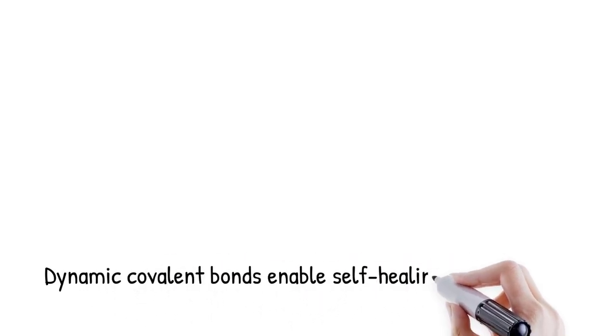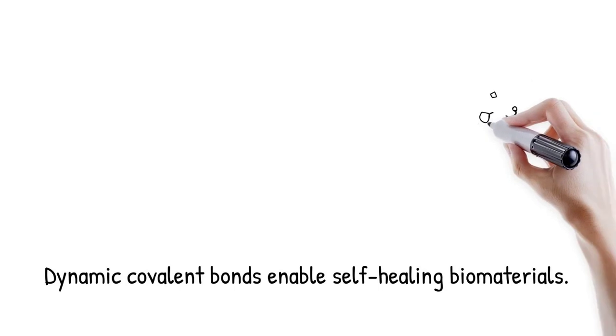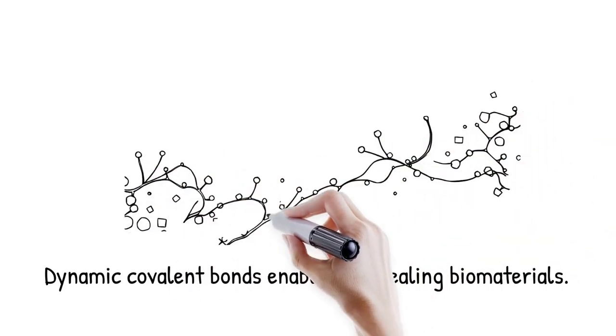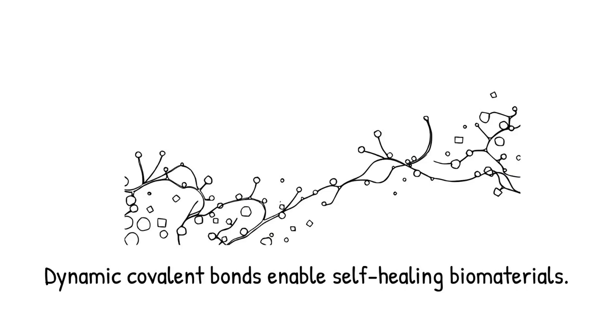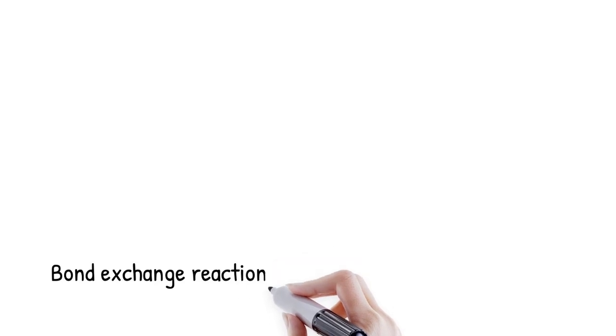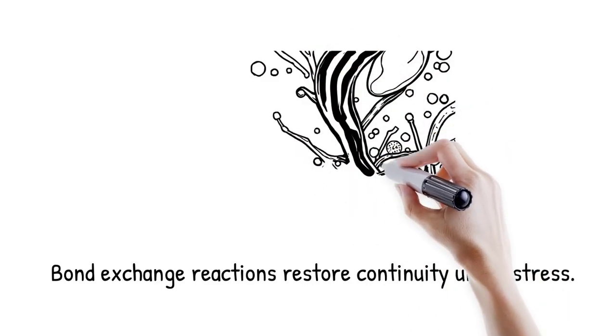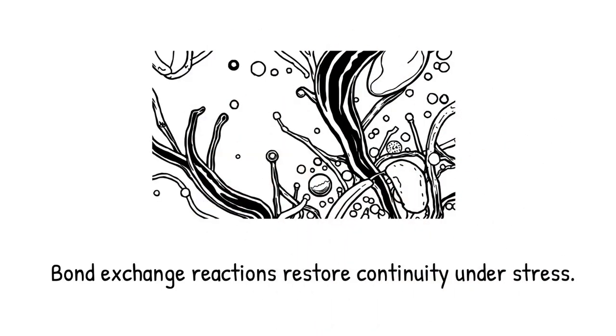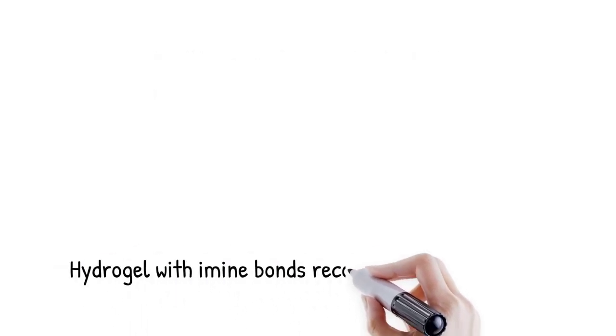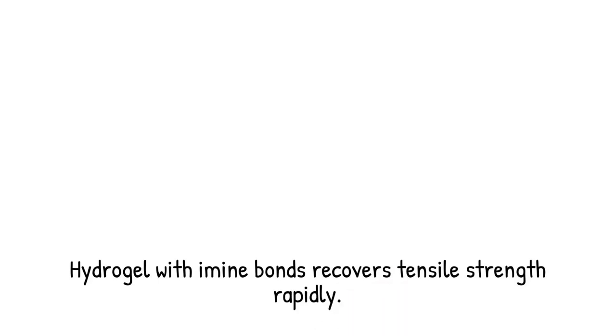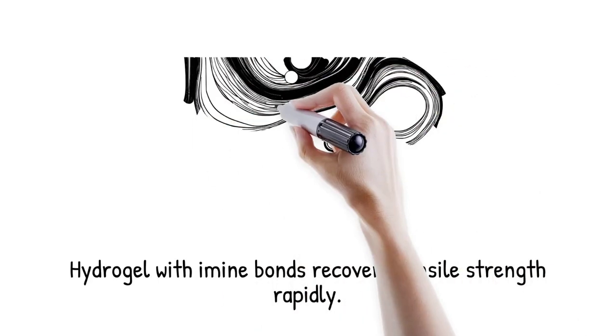Self-healing biomaterials often incorporate dynamic covalent bonds, such as disulfides, imines, or boronate esters, that reversibly break and reform under physiological conditions. These bonds provide structural integrity, yet allow network reconfiguration when damaged. Under stress or cut, bond exchange reactions locally cleave and reconnect, restoring mechanical continuity. The kinetics of bond exchange can be tuned by pH, temperature, or catalyst concentration to optimize healing speed. Because the bonds continually equilibrate, the material maintains adaptability far from thermodynamic equilibrium.